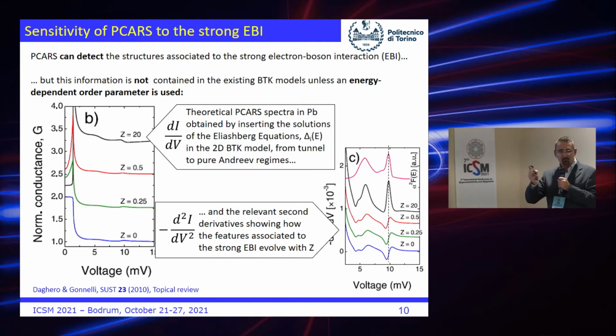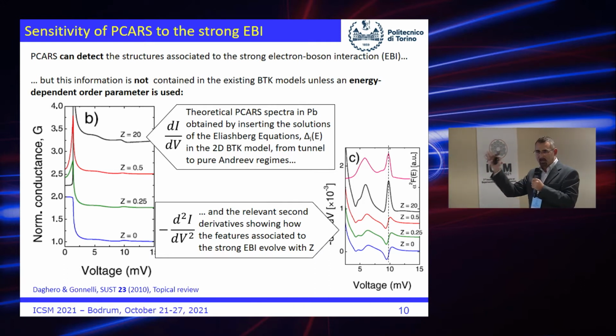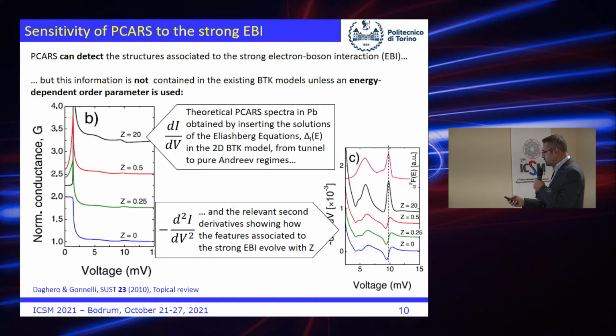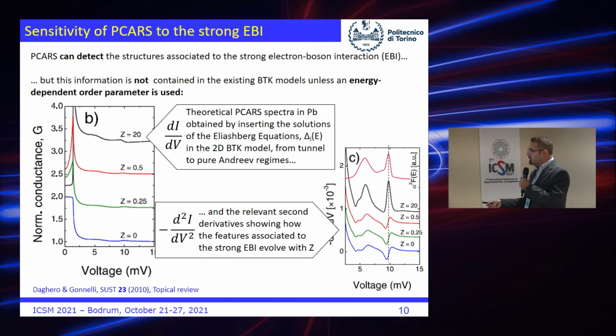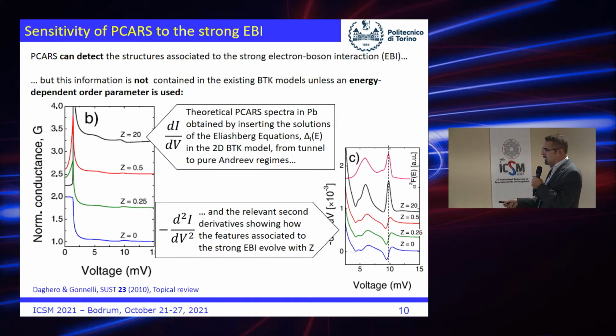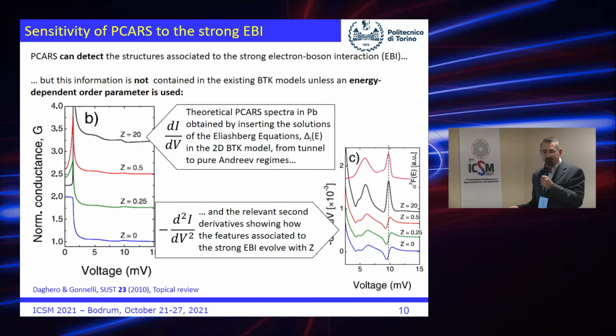So Z high means tunneling, an NIS junction. Z equal to 0 means instead no insulator, NS. So you see that there are clearly these structures, and in the tunneling regime, if you calculate the second derivative, you obtain this black curve, which reflects exactly the alpha square F of lead.